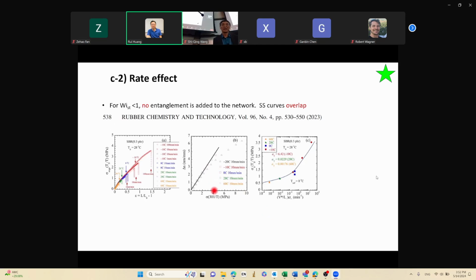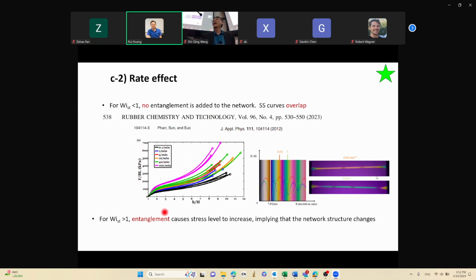Rate effect, this is a marvelous thing. I think Oscar just said there is very little of that data. Indeed, we just published this data last year. So this is a sample that has a notch, at different rates, different temperatures. They all fall on top of each other, indicating this is purely elastic stretching. But you can get the so-called rate effect or viscoelastic effect.